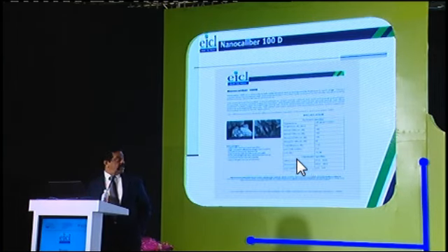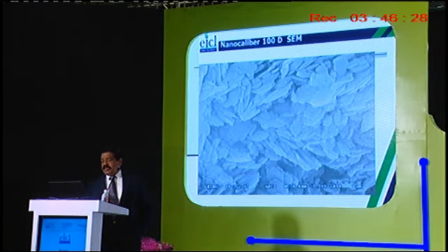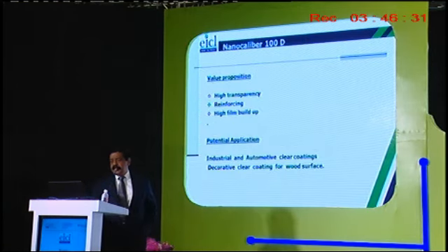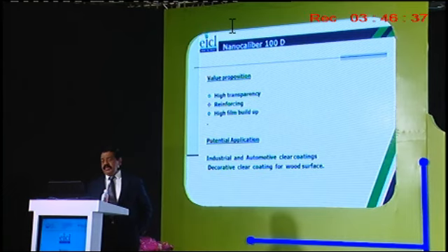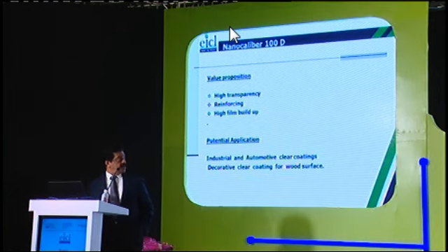Now we also have a grade called Nano Caliber 100D, and you can see the finer nanoparticle size, where it can be used for high transparency, reinforcement, or high film build. The potential applications include industrial and automotive clear coatings, and decorative clear coatings for wood structures. The advantage of nanomaterials in clear coatings is that they retain transparency and gloss levels, but also enhance high film build-up, thereby increasing the durability of the coating.